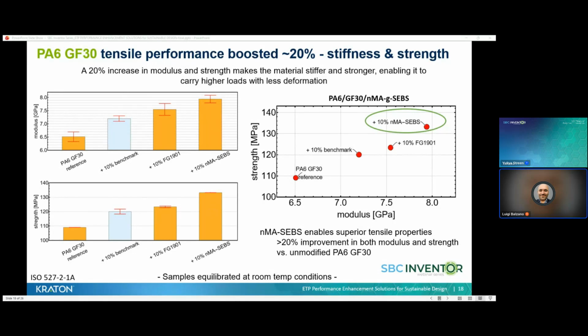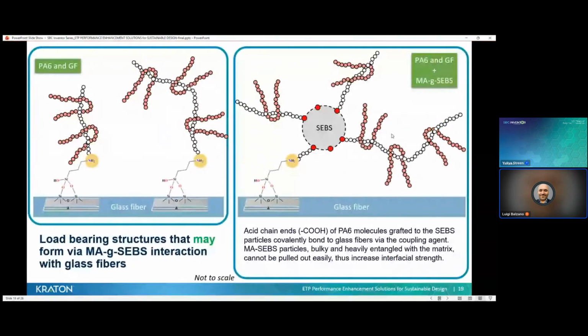Polyamide is hygroscopic, and for putting the absolute values of the properties into context, it is important to notice that the samples were fully equilibrated at room temperature, which means that prior to testing, they had very long time to absorb most moisture from the atmosphere, and at the point of testing, they contain something in the neighborhood of 3% of water. But how to explain these unexpected results? Here is a plausible explanation.